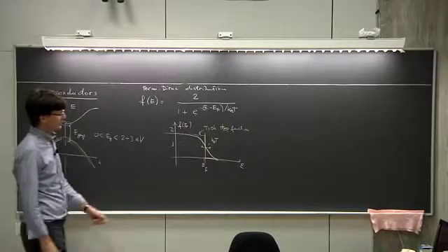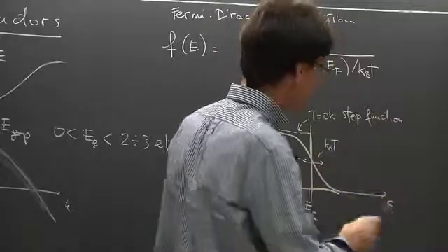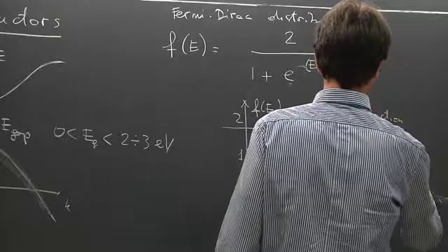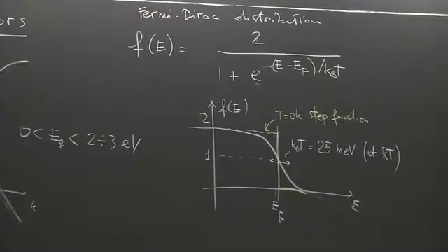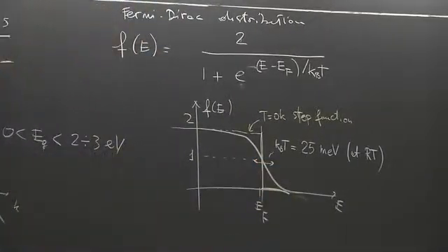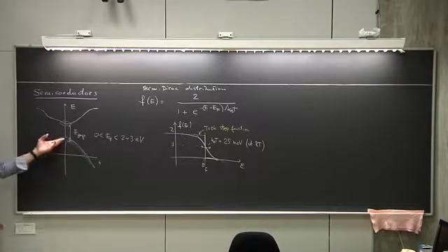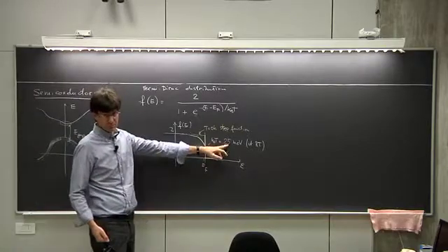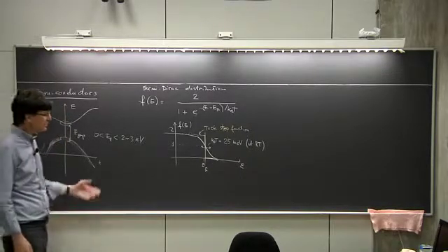Now, we also argued that the value of kBT at room temperature is 25 millielectron volts. Okay. So this width here is very small compared to typical band gaps. It's quite rare to find materials where the band gap is so small. They do exist, but they're quite rare, of course. If they do exist, you can expect a large amount of electrons being promoted in the upper band. However, this is rarely the case.